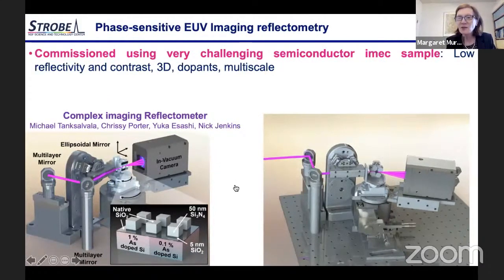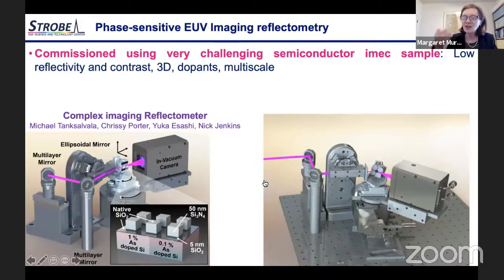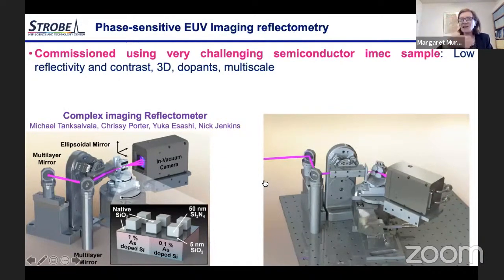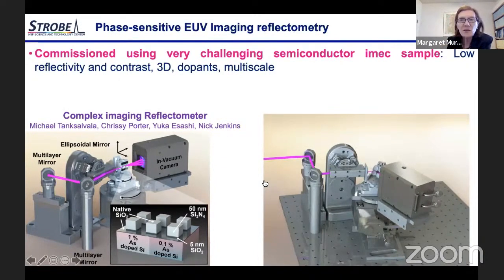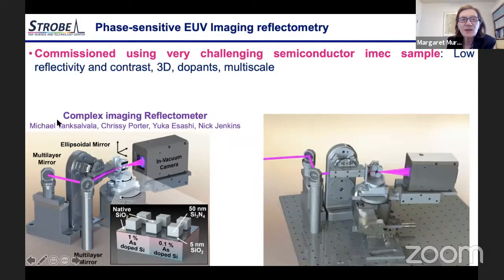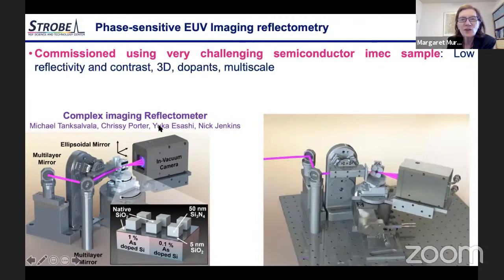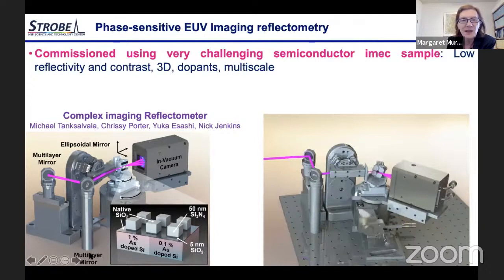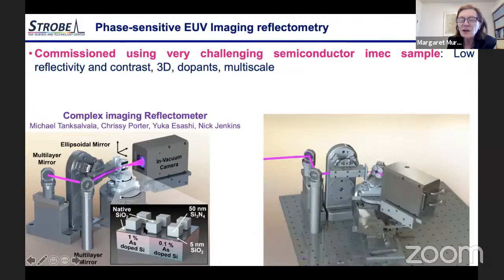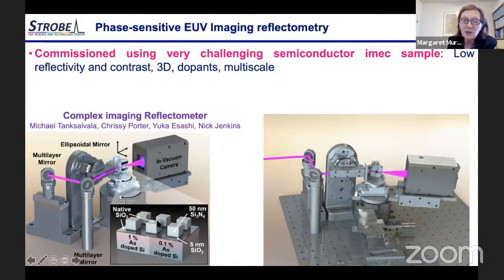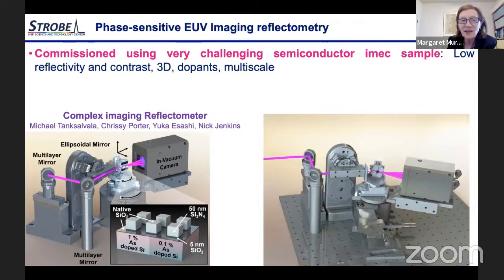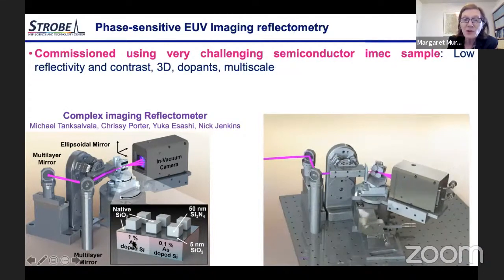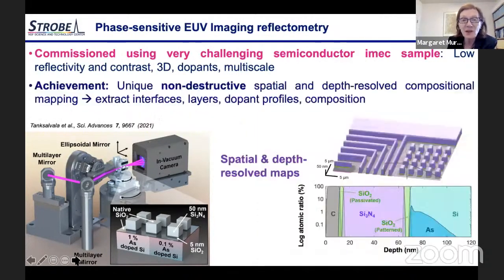This was the most complicated microscope we've ever built, because what it has to do is scan multiple different angles and then do this ptychographic, or overlap scanning, motion at each angle. I have to give a lot of credit to an amazing group of students, Michael and Chrissy and Yuka and Nick, who built this and then commissioned it. And then imec provided this very nice nanostructure that had a lot of challenges. It had very low reflectivity. It had multiple height samples. It had different regions that were doped differently underneath.